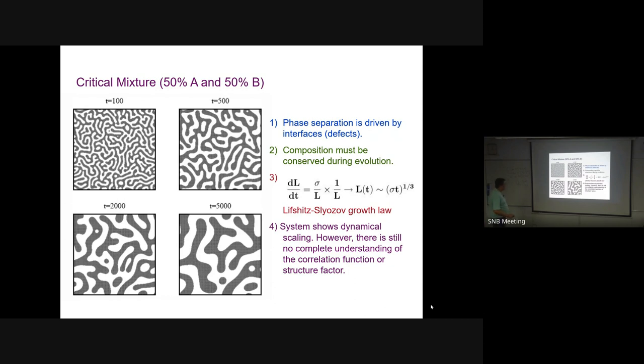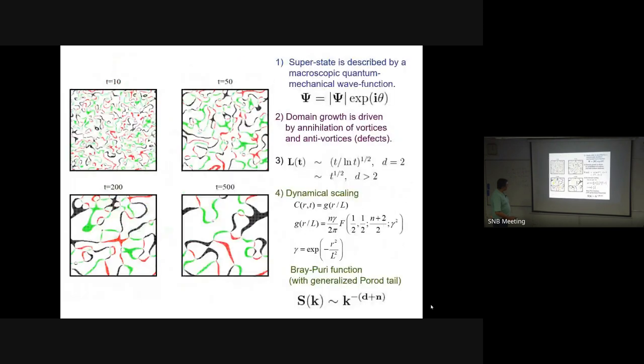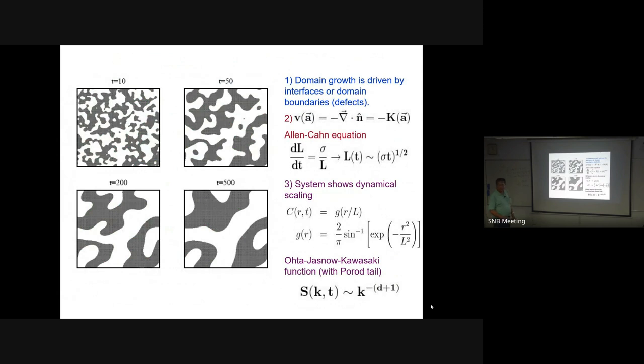The t^(1/3) law applies for diffusive growth. If you add hydrodynamic effects - as in oil-water phase separation - other avenues of transport open up since fluids can transport material faster than diffusion, and you get a crossover to other growth laws. The system shows dynamical scaling - this guy (later time snapshot) is statistically similar to that guy (earlier time snapshot), just a blown-up version.